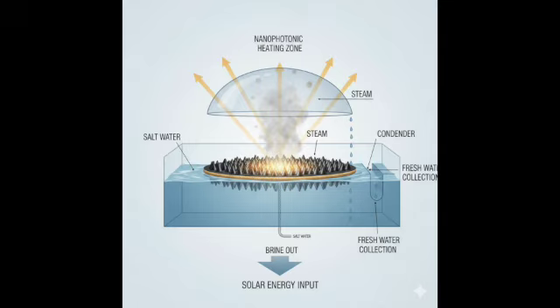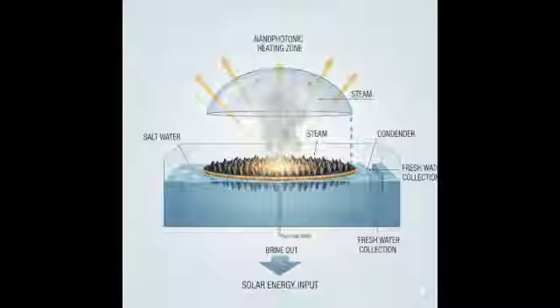on a nanoscale. Researchers created flexible, thin films of black gold, nanostructured gold, that absorbed 91% of light in the 400-500 nanometer range. Self-assembled aluminum nanoparticles showed over 96% absorption across the entire solar spectrum. That sounds incredibly efficient. What's the catch? Cost and stability. Noble metals like gold are obviously very expensive. More common metals like aluminum are prone to oxidation, which can degrade their plasmonic properties over time, especially in harsh aqueous environments. Finding cheap, stable, and highly plasmonic materials is an ongoing challenge.